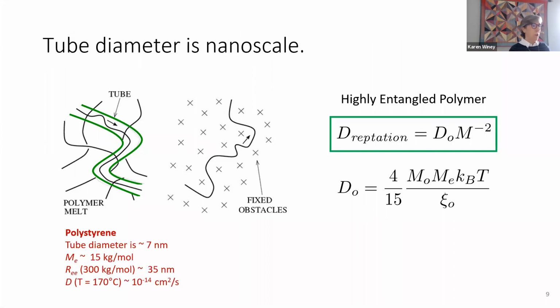Just to remind you, the length scales involved in polymer reptation: the tube diameter is only a few nanometers. In polystyrene, it's 7. The end-to-end distance for reasonably high molecular weight polystyrene is about 35 nanometers, and you have a diffusion coefficient of 10 to the -14. But these are nanoscale. So the question that we've asked for over a decade now is how polymer diffusion can be impacted by nanoparticles that are on the same length scale.